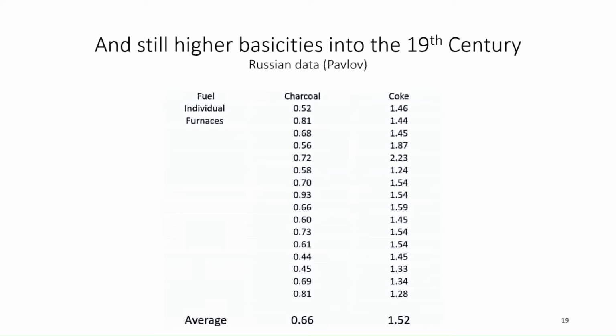Just to emphasize the point, these are basicities reported by a chap called Pavlov, who was a Russian, and he reported all the slag basicities that were used in both the charcoal furnaces and the coke furnaces that were run in Russia in the middle of the 19th century. And you can see here that the coke furnaces had a basicity of over 1.5 on average, whereas the charcoal furnaces got away with 0.6, 0.7. So the important thing about raising the temperature of the blast furnaces was to be able to raise the basicity to be able to remove the sulfur.